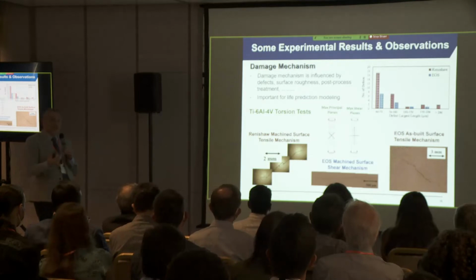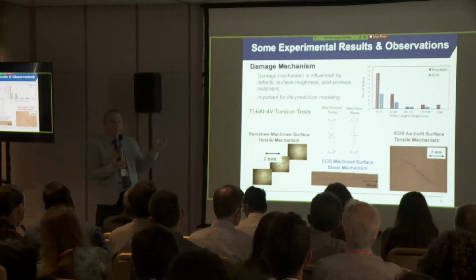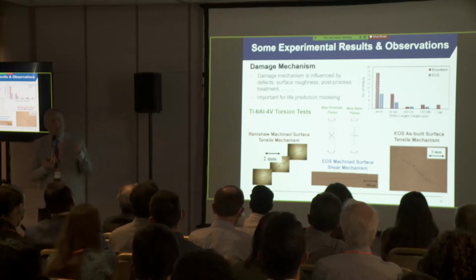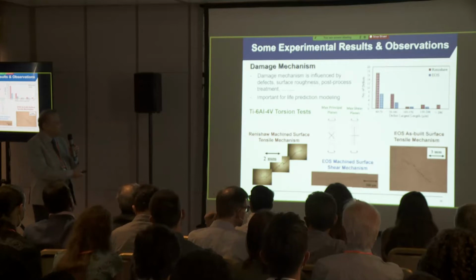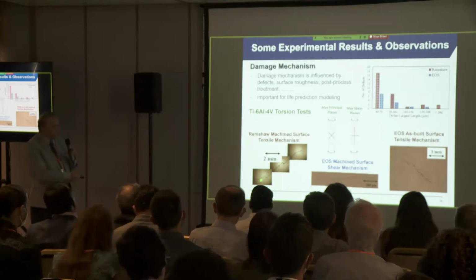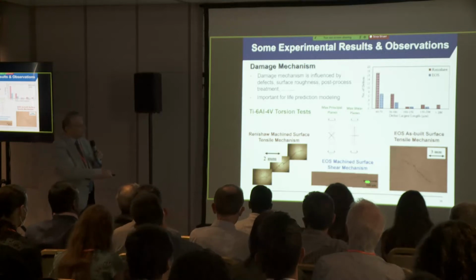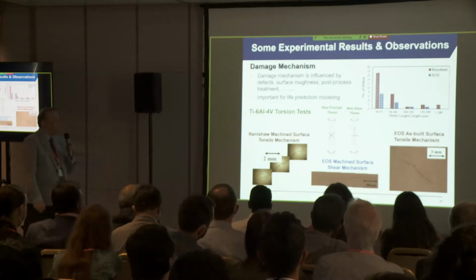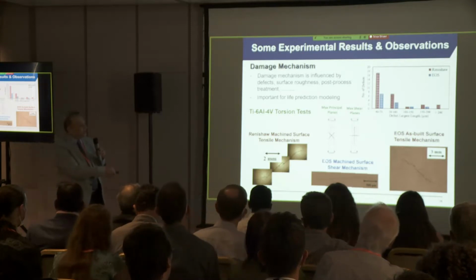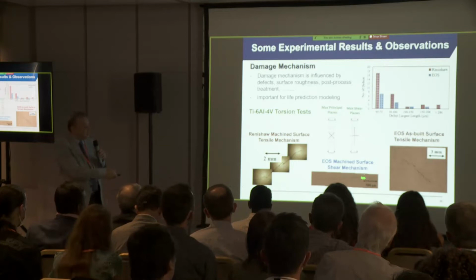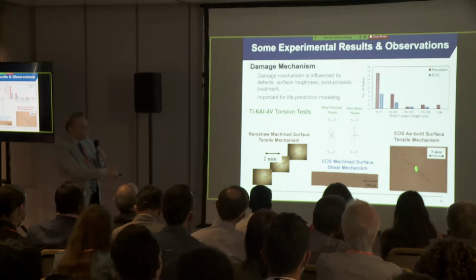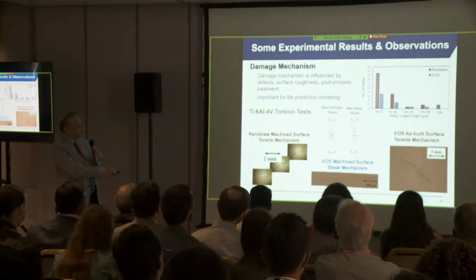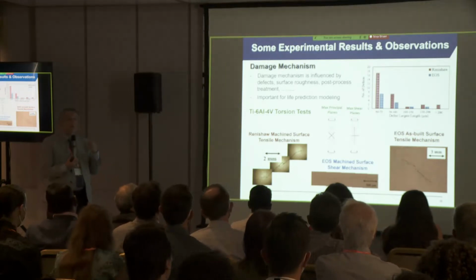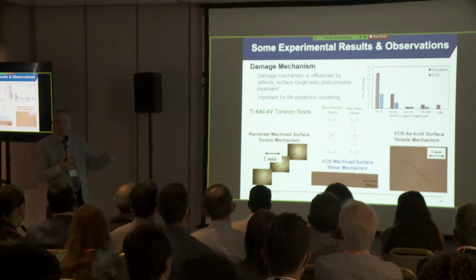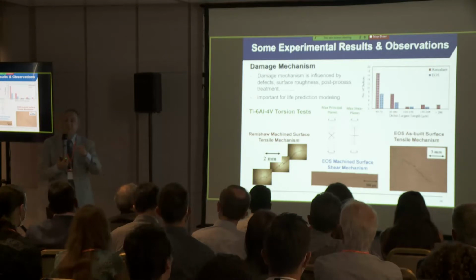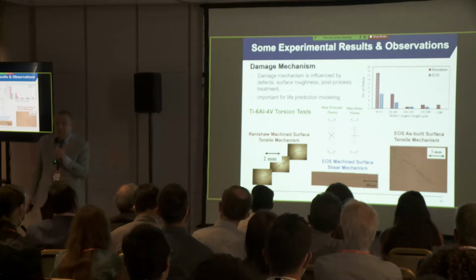Damage mechanism can change quite a bit depending on the kind of variations I talked about in terms of defects, in terms of surface roughness, in terms of manufacturing process parameters. For example, in torsion loading, it can be tensile, along a tensile plane, or it can be shear along the horizontal plane. But even for a material that doesn't have a lot of defects resulting in shear, the as-built surface will change that to a tensile mode. So depending on the variations, we need to know what the damage mechanism is, because that will have significant implications in the life prediction methodology we will use to predict the life.